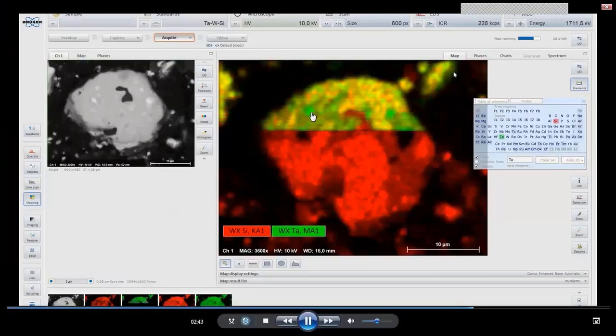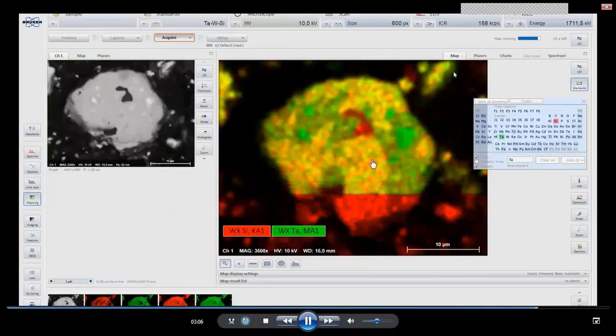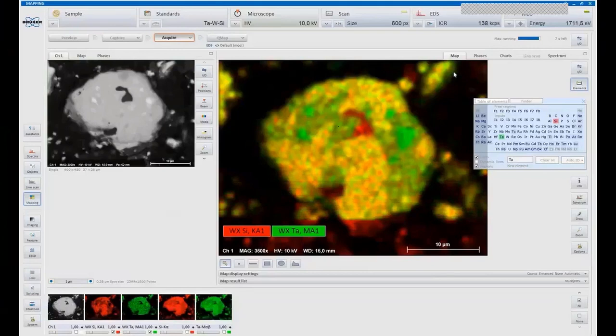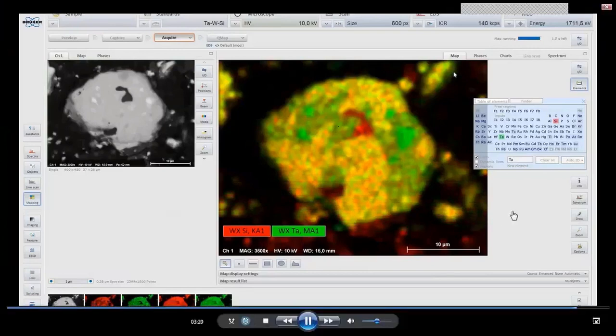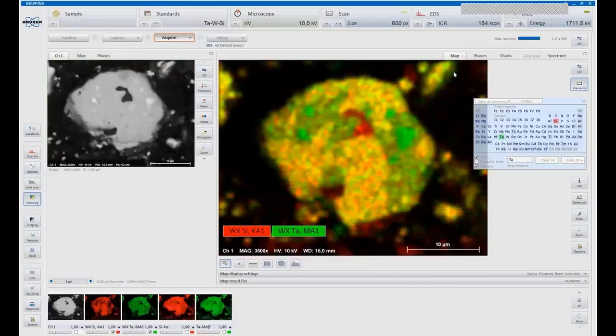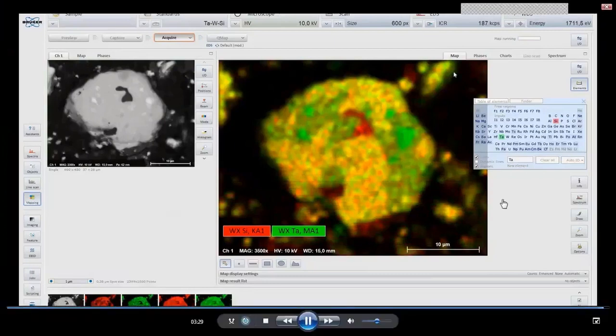We see some areas where there's pure tantalum, so bright green colors in these spots, whereas in some areas we have a mixture of tantalum and silicon with the yellow colors, and some areas which are missing more of the silicon. Here are areas only having silicon and no tantalum. You might say this is a quite blurry image, but remember it's mapping for just a single minute. So when you're mapping for several minutes, then you will get a much clearer image. You will get much better resolution. So that's how mapping is done.